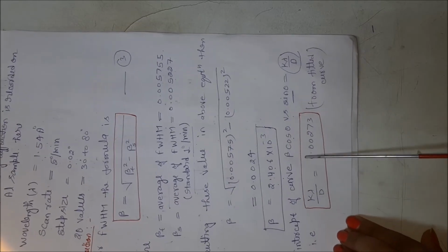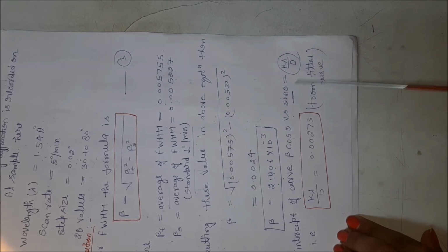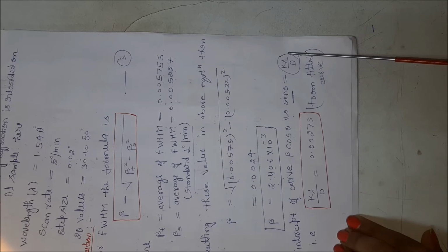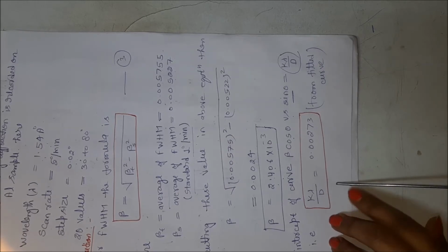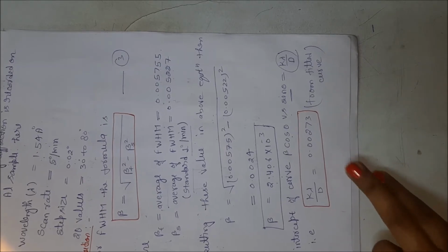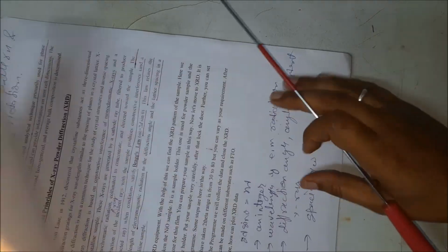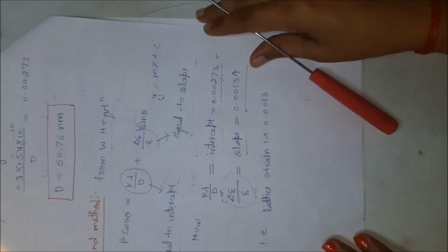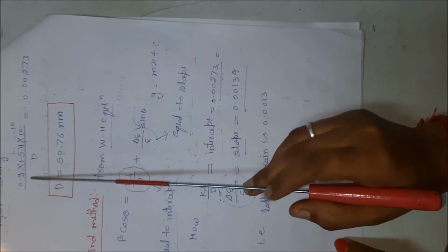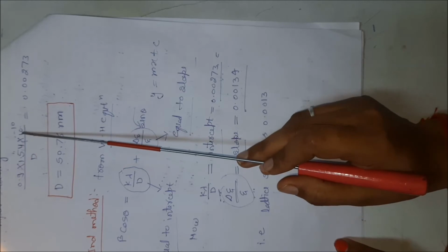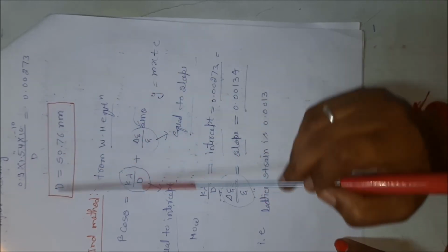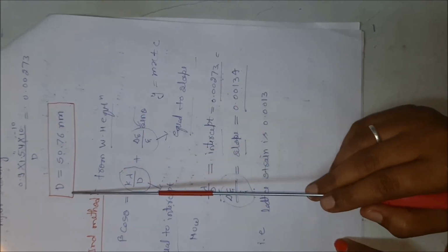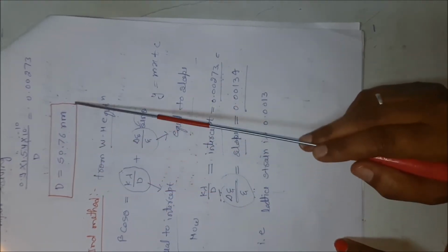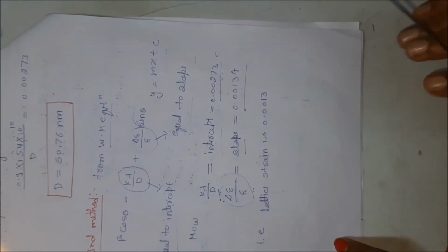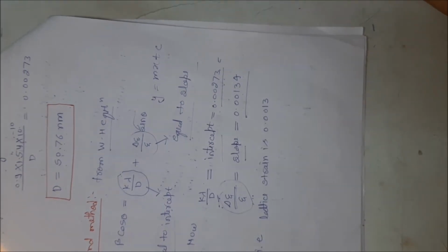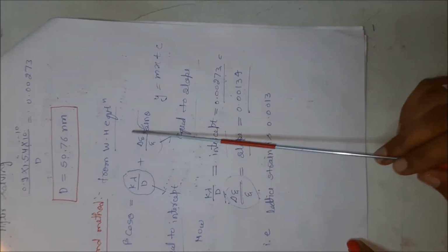The intercept of the curve beta cos theta versus sin theta is equal to the Scherrer formula k lambda upon d. This means that k lambda upon d equals 0.00273. Now, putting the values of k and lambda, we can calculate the crystallite size. The value of k is 0.9 and lambda is 1.54 into 10 to the power minus 10 upon d. After calculation, we get the crystallite size as 50.76 nanometer. With the help of the WH equation, we can also get the crystallite size and the lattice strain.